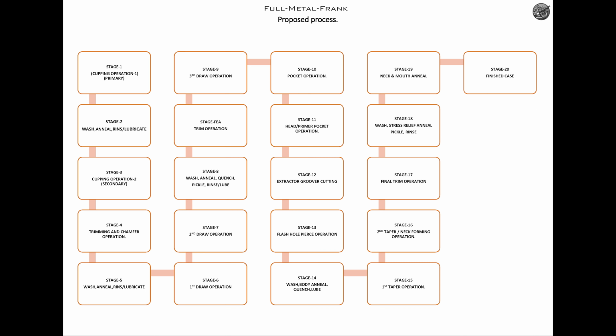Before we jump into the details, here's a quick overview of the entire proposed manufacturing process. In total, the case forming process consists of 19 major stages, starting from the primary cupping operation and ending with the final neck and mouth annealing. Throughout these stages, the brass undergoes multiple forming, machining, and inspection operations to progressively transform a flat blank into a fully formed cartridge case. Because the material experiences significant cold work during the drawing and forming operations, annealing is required several times throughout the process to restore ductility and control the hardness gradient along the length of the case.